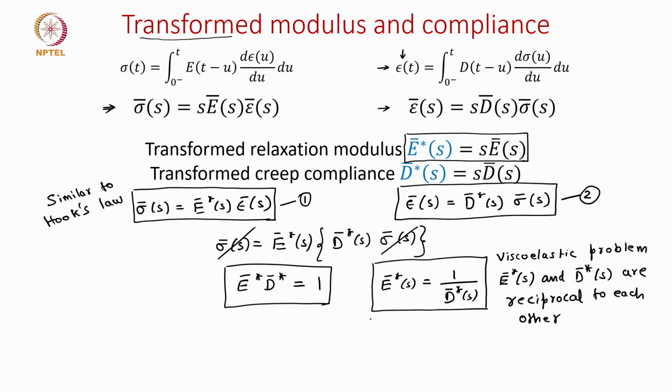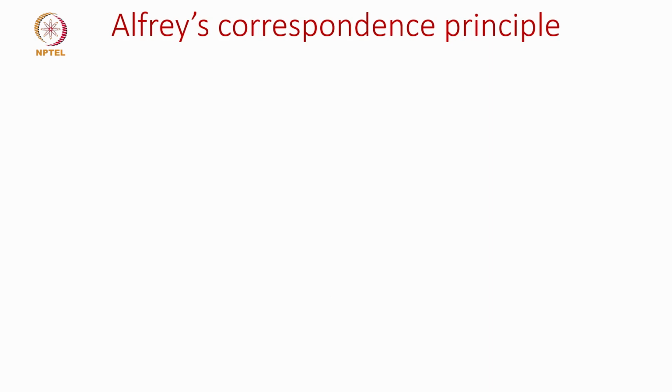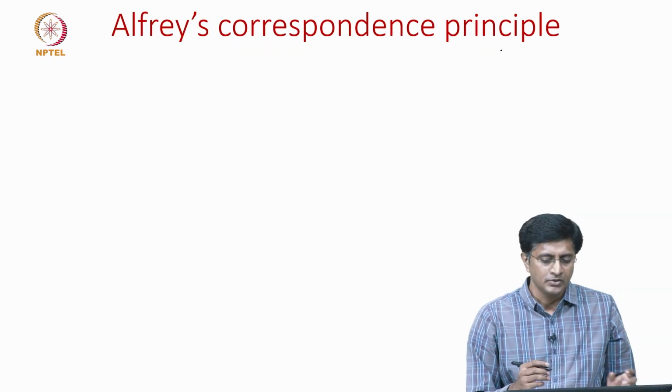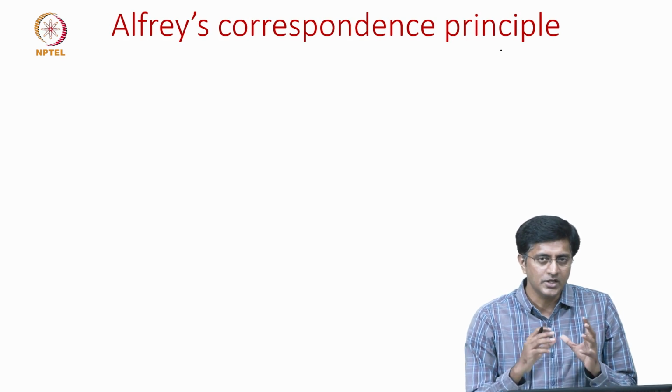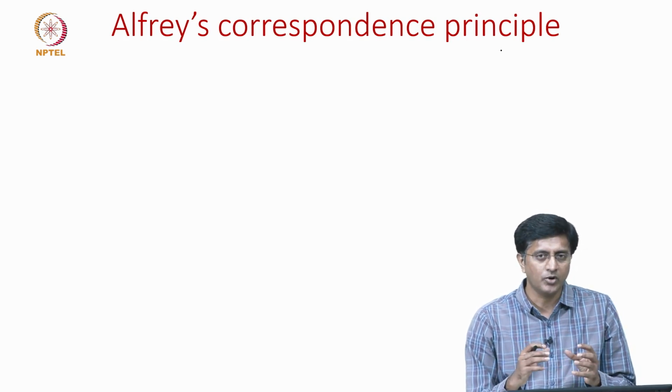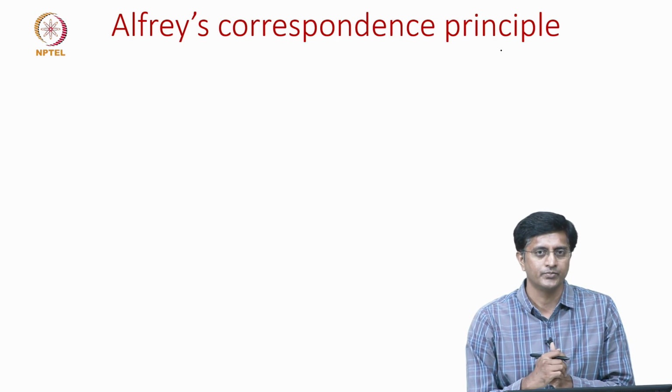So, this is another very important conclusion we came to, saying that we are now able to relate the modulus and the compliance, but this relation we are able to show in the Laplace domain. So, using these observations, now we will come to the most important concept of this video, which is Alfrey's correspondence principle. This principle gives a step by step procedure about how to solve a viscoelastic problem.